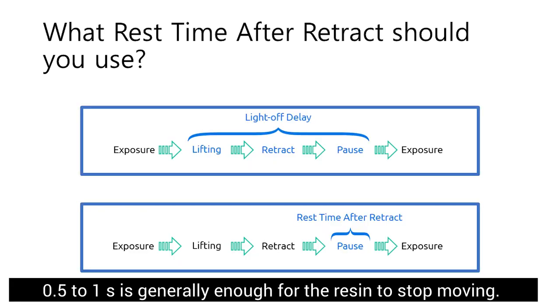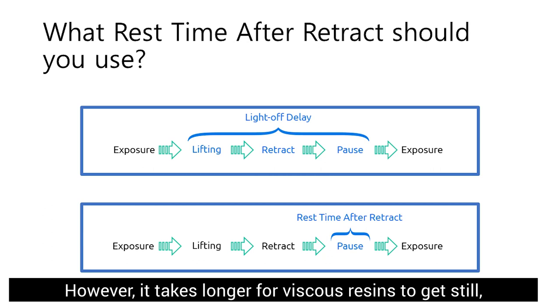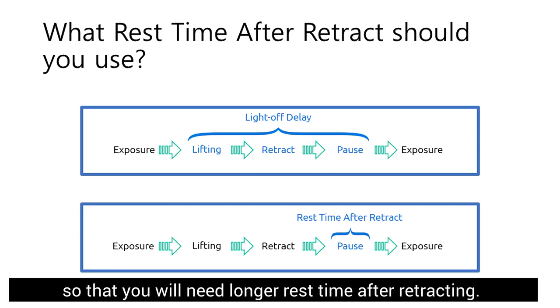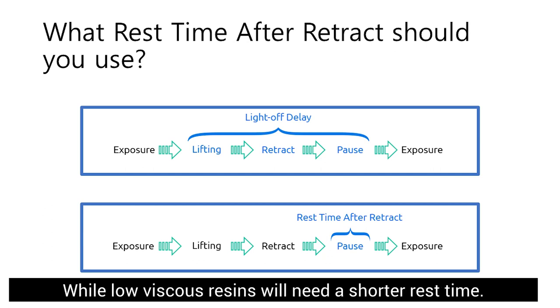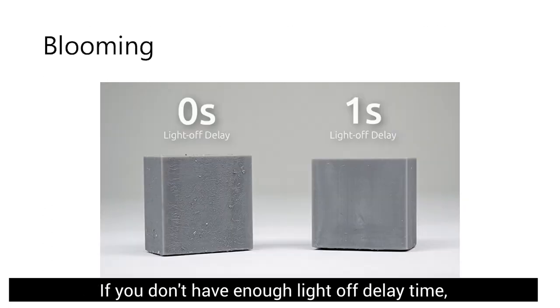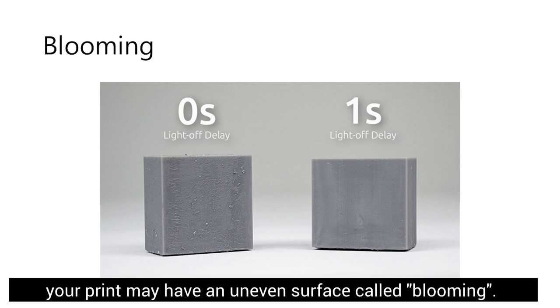0.5 to 1 second is generally enough for the resin to stop moving. However, it takes longer for viscous resin to get still, so you will need a longer rest time after retracting. While low viscous resin will need a shorter rest time. If you don't have enough light-off delay time, your print may have an uneven surface called blooming.